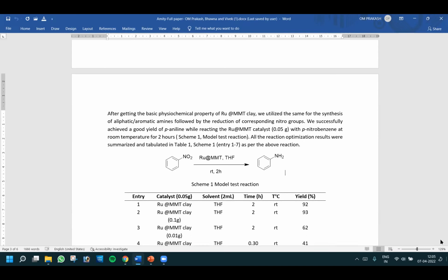Conclusion: we successfully synthesized ruthenium exchanged MMT clay using a wet impregnation cation exchange method. The same was characterized by X-ray diffraction study. Further, ruthenium MMT clay was a useful catalyst for the synthesis of aliphatic and aromatic amines by reduction of the corresponding nitro group. We obtained all the amines in good yield. Additionally, we obtained 4 times catalyst recycling with good yield of reaction products. Thanks, sir.